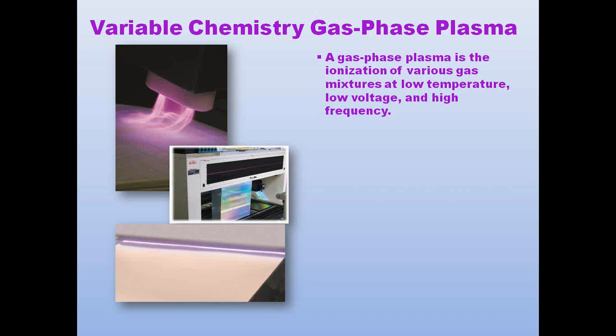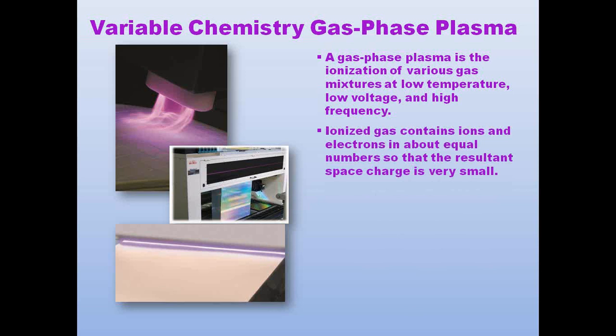The principle is similar to the flame plasma and air plasma technologies insofar as the gases or the mediums that become the interface with the surface of the material are being ionized, so you have ions, electrons, and other species that are bombarding the surface. Ultimately, with a variable chemistry plasma, however, you have a charge-neutral effect. This charge-neutral effect is a result of a balance between these different charged species so that there is a discharge, if you will, of existing charge from the surface of the material.